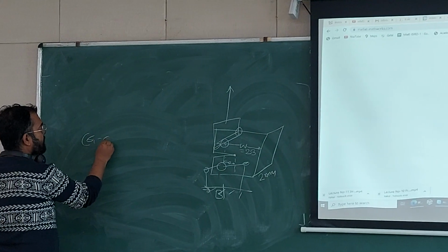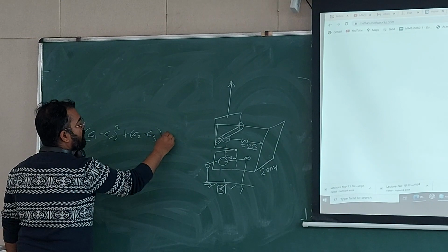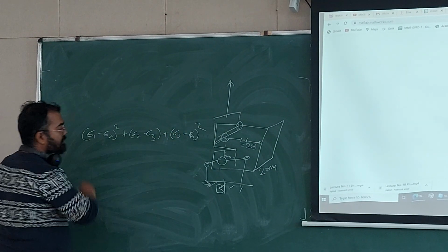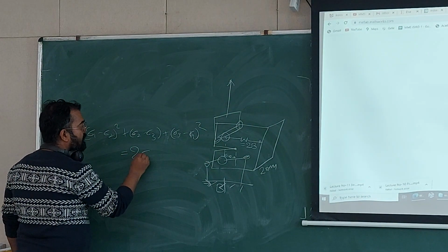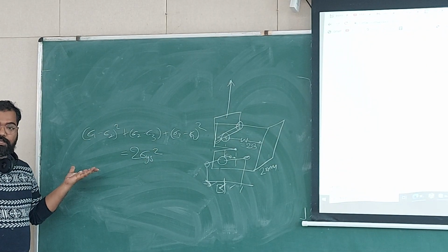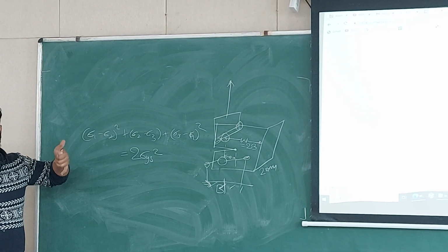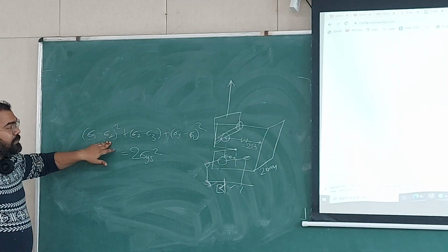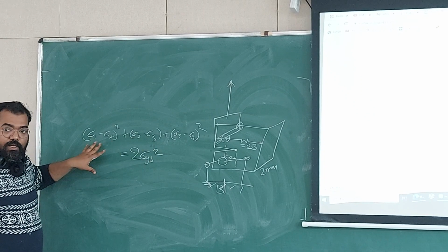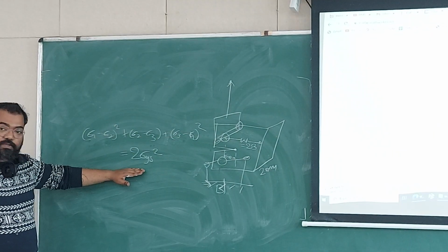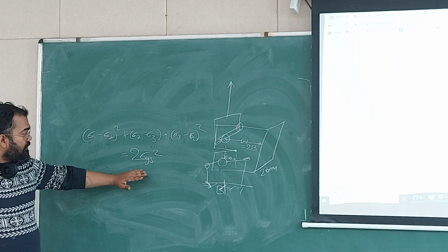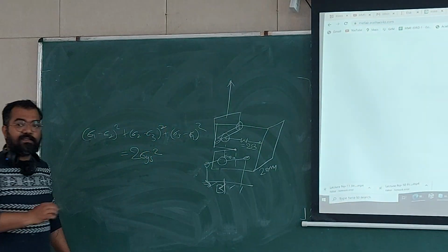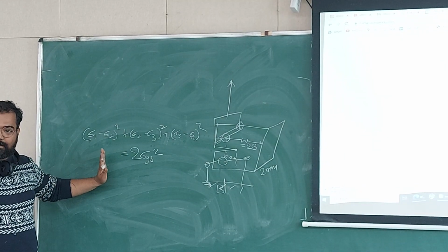You see. Okay. So forget about this curve; we'll discuss that later. The von Mises criterion is the square root of (sigma 1 minus sigma 2) whole squared plus the summation of the differences of all other principal stresses. This is equal to the following if it is a uniaxial condition and sigma 1 is giving you sigma ys, which is a principal stress. Then sigma 2 will become 0, sigma 3 will become 0. Squared. So what will you have? 2 sigma 1 squared will be equal to 2 sigma ys squared, so sigma 1 is equal to sigma ys. Right? Square was missed. Where was it missed? The second term. Okay, fine. So this is von Mises.